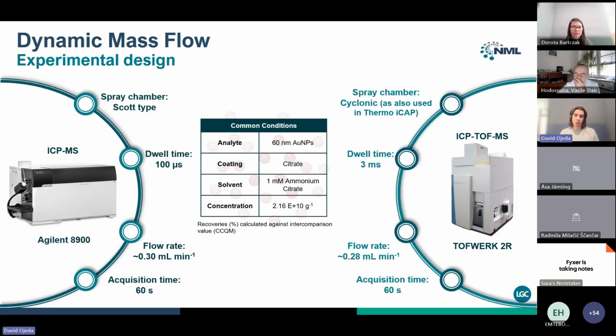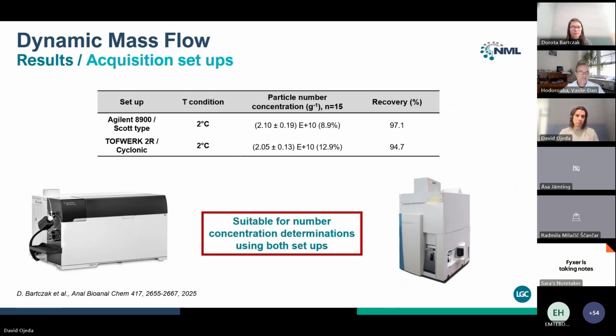And then we compare the performance of these 2 different instrumental setups for the same flow rate conditions and acquisition times. The sample that was decided for these studies was 60 nanometer gold nanoparticles in citrate. To check the performance of the DMF, we compared the results that we obtained against a specific number concentration value from an interlab intercomparison study at a CCQM level. So we are presenting all the results in terms of recovery against this concentration value.